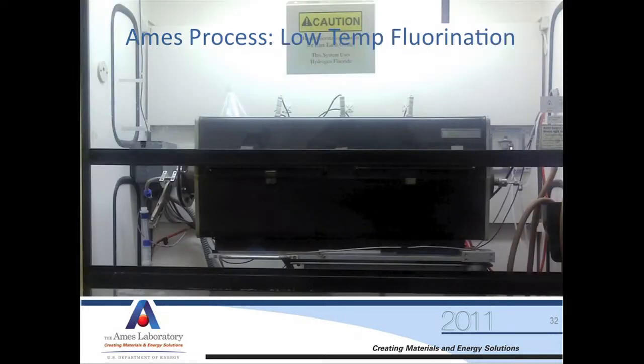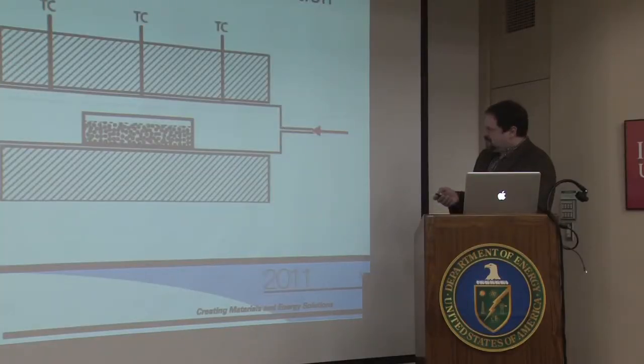Our fluorination starts in a fluorination furnace, which is really pretty boring. It's just a box with a tube through the center of it. Even the schematic is kind of not very thrilling, is it? We feed in HF gas and argon. Comes over here, get a gas-solid reaction, produces the rare earth fluoride, water is a byproduct, and we push that all out the end in terms of a gas. We take that high purity fluoride